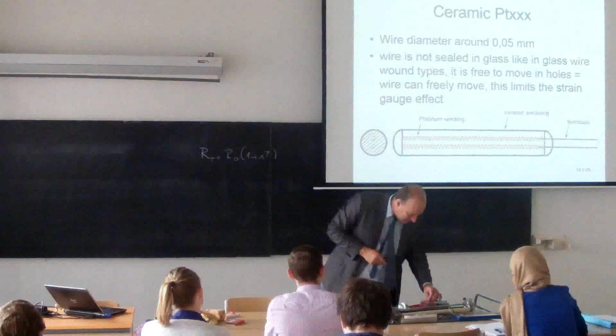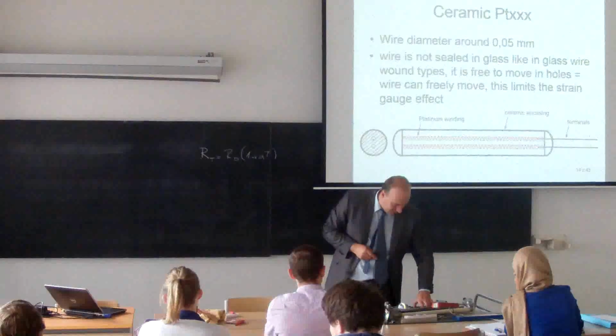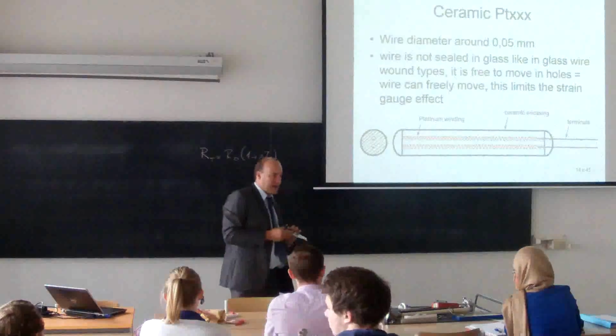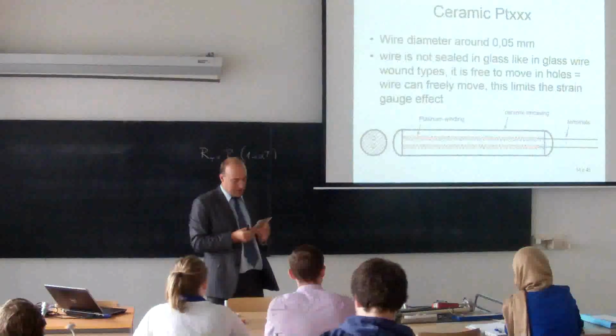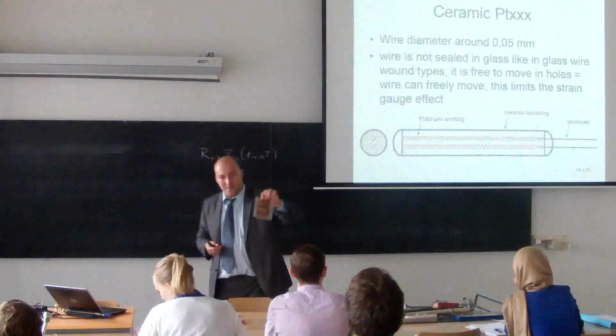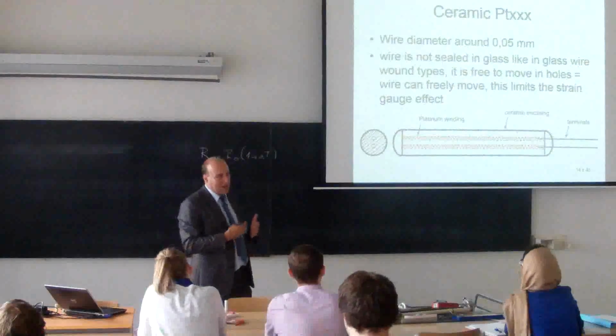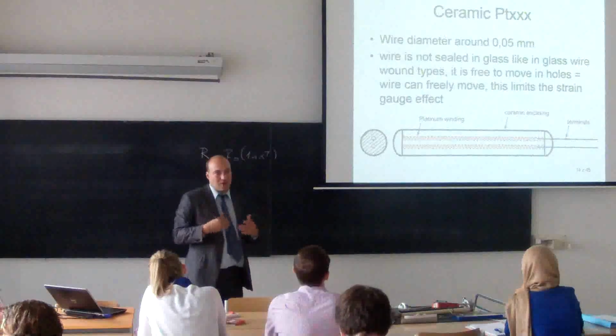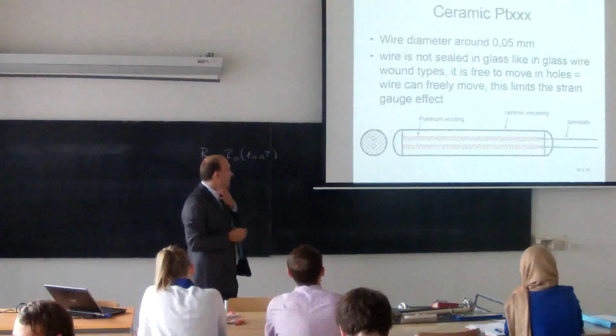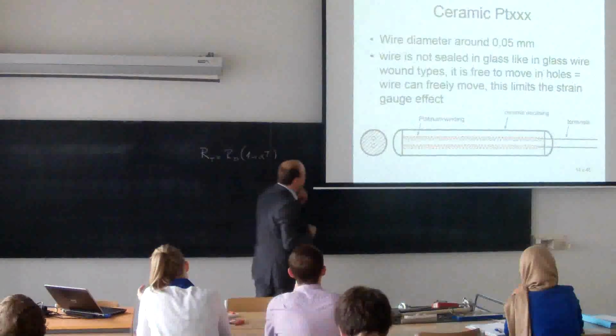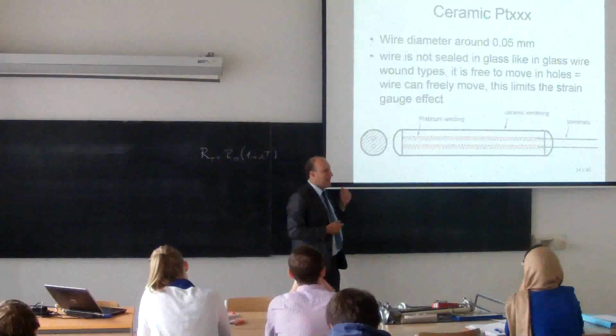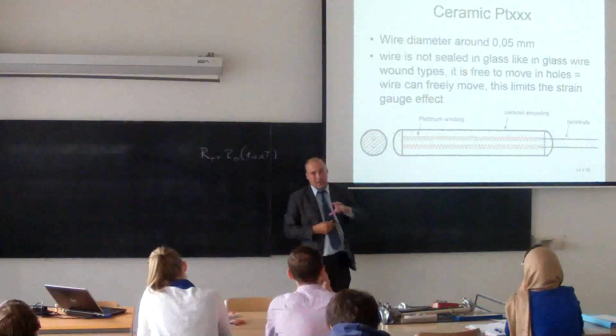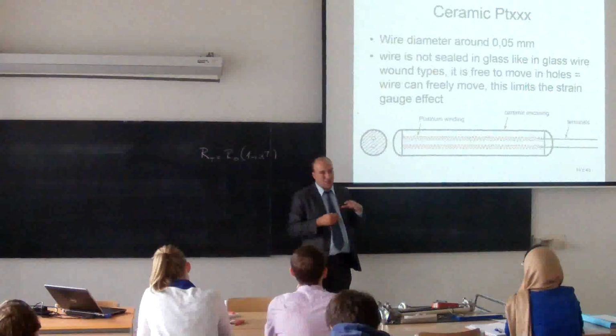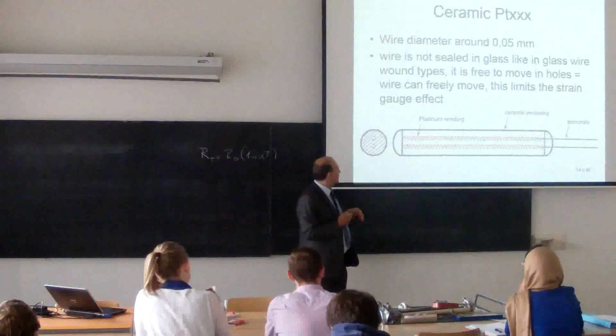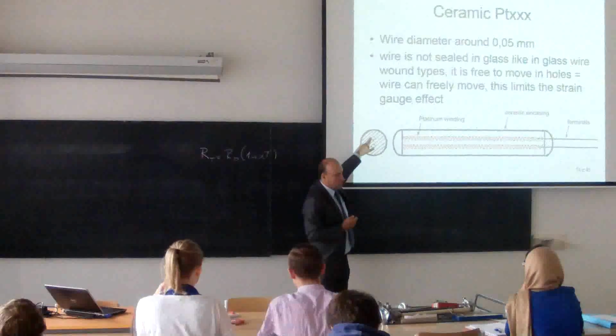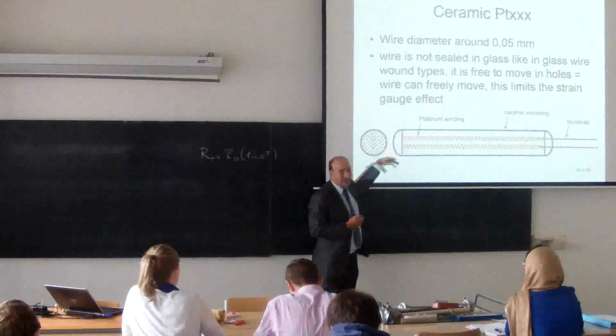The second version of the PT100 is encased in ceramics. So it's a ceramic PT100. The principle is the same. It is thin platinum wire, typically diameter 0.05 millimeters, very thin. And this is wound and placed inside the ceramic casing. The difference between the ceramic casing and the glass casing is that the glass casing is completely covered with the glass. For ceramics, we have 2 holes, and the wire is placed as a coil inside.